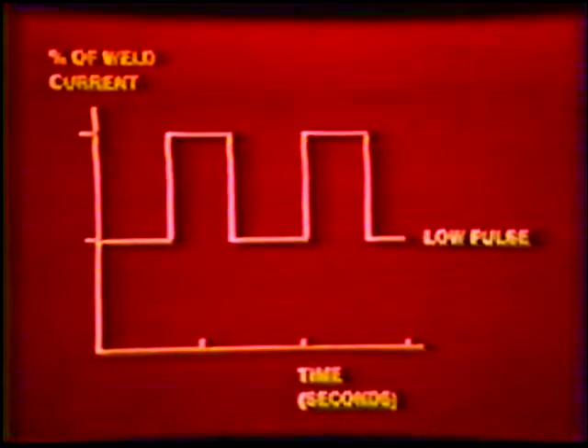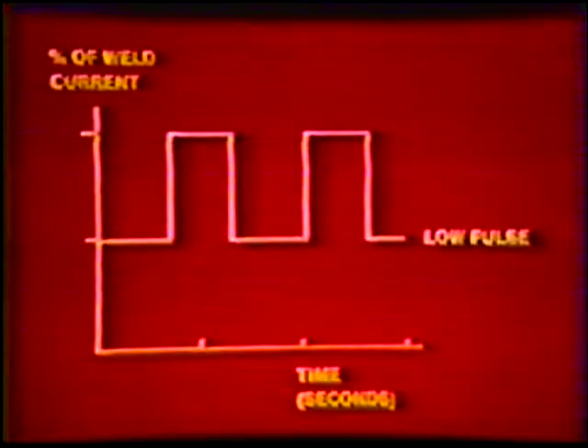On many programmers, pulsed current is available for additional control of the welding current. Pulsed current allows the current to fluctuate from a high level, which provides penetration, to a low level, which allows the weld to cool slightly. This type of current provides complete penetration without an excessive buildup of heat in the weld zone. The weld actually appears like a series of overlapping spot welds.